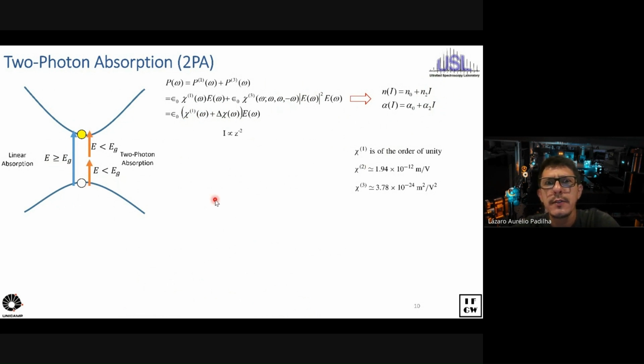So one thing that's interesting is that if you have a focused laser beam, the irradiance is proportional to z to the minus 2, where z here is the beam waist, right? On the other hand, if you think about fluorescence or emission, you're going to think that this is proportional to the irradiance for linear absorption times how much the material absorbed, which is proportional to alpha. So if you think about the emission caused by two-photon absorption, you're going to realize that it's proportional to I squared.